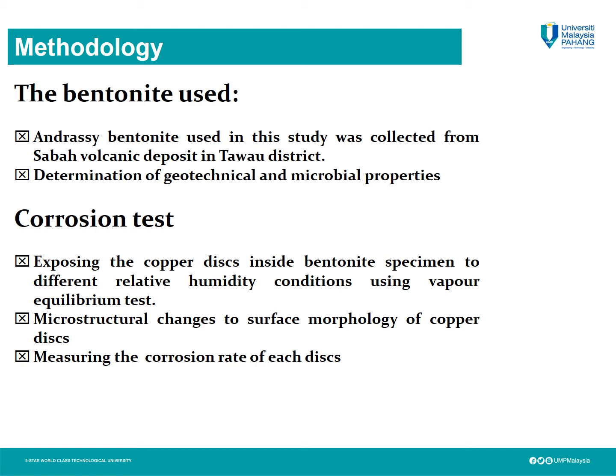The type of bentonite, which is known as Andrassy bentonite, collected from Sabah volcanic deposit in Tawau district, Malaysia, was used. The first step was to determine the geotechnical and microbial properties of this specific bentonite. Later, a corrosion test was performed by exposing a copper disc inserted into bentonite specimen to different relative humidity conditions using vapor equilibrium tests. Then the microstructural changes to the surface morphology of the copper disc before and after the test were determined. Lastly, the corrosion rate of each disc was measured.